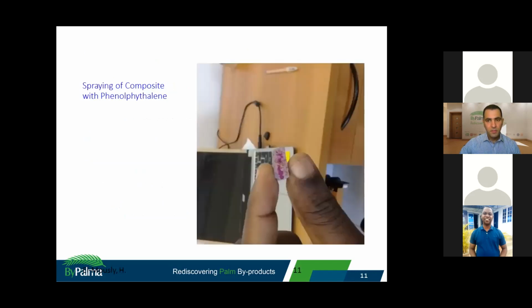But in between, every 3 hours, you cut a fraction of your sample and spray it with phenolphthalein. When you spray with phenolphthalein, the colorless part shows the area that has been injected very well with CO2.